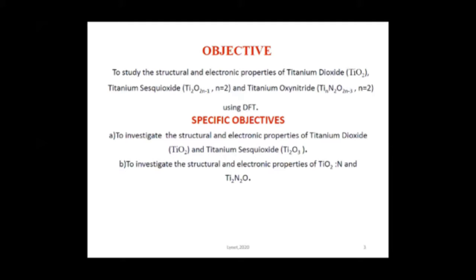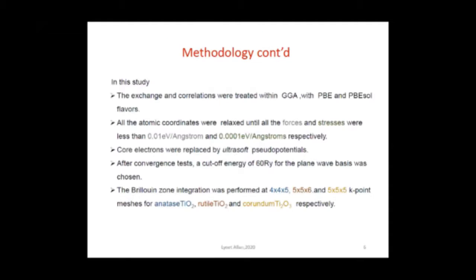Fine. I am already at the 6th slide, but I can see my slides are not moving. I was talking about the methodology and stating that we treated the exchange and correlation within GGA, generalized gradient approximation, with two flavors, the PBE and PBEsol, just to check on how these affect the lattice parameters. And we relaxed all the structures. The core electrons were replaced by ultrasoft pseudopotentials, which offer faster convergence. And after going through the standard convergence procedure, a cutoff energy of 60 Ry was realized, and the Brillouin zone integration was performed at the converged K points for those specific materials.